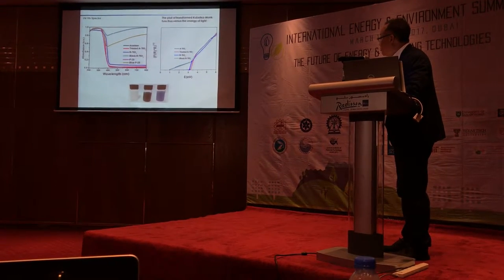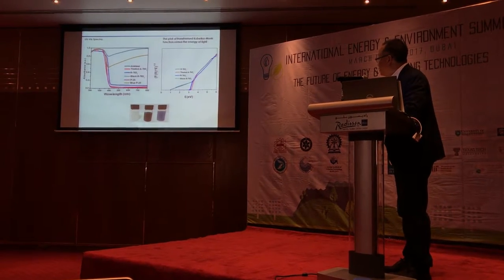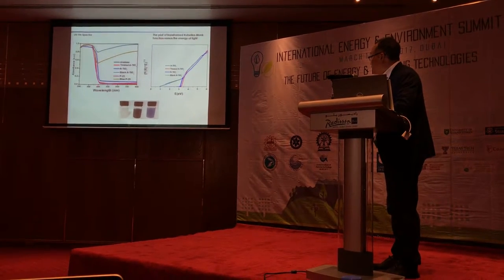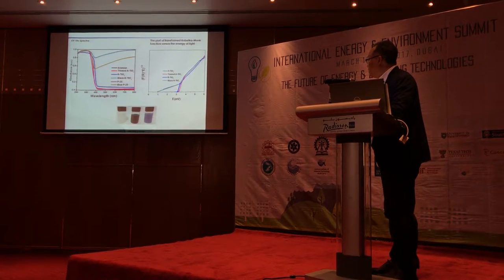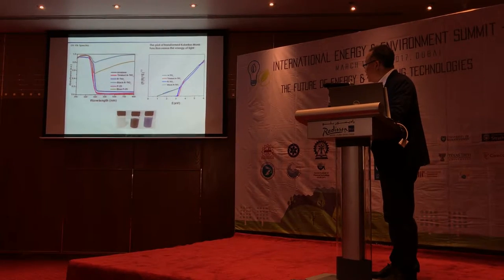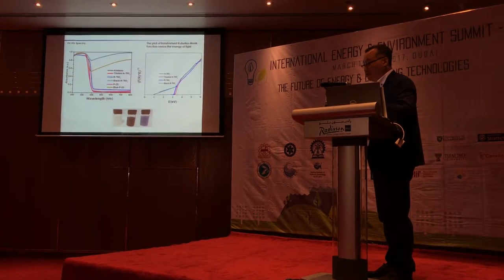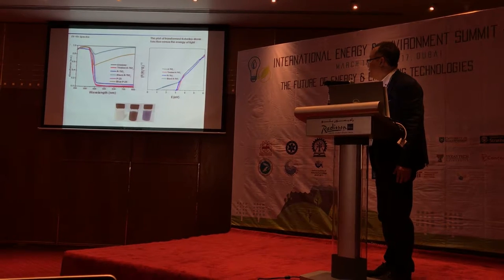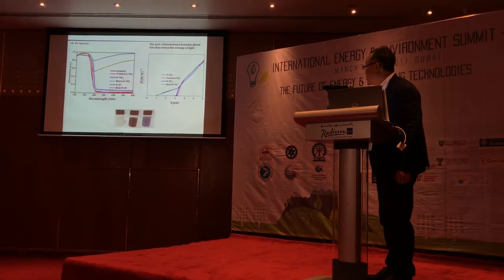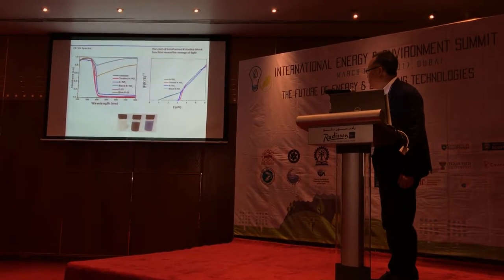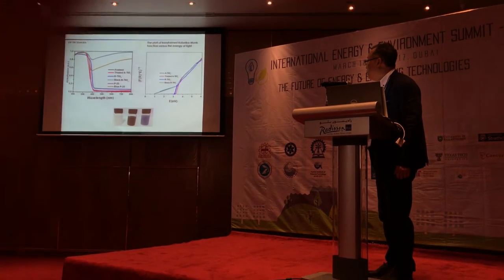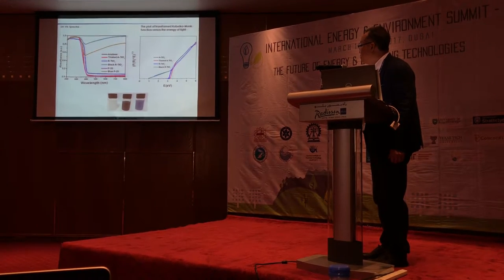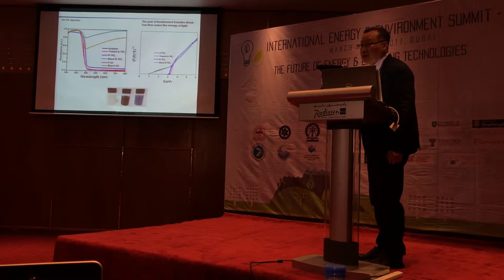Usually, TiO₂ can only be observed in the UV zone, from 200 to 400 nm wavelength, and did not absorb in the visible region from 400 to 800 nm. But with our treatment using the reducing agent lithium EDA, the black one absorbs visible light up to the IR. And the blue one also shows visible light absorption, with slightly less intensity than the black one.